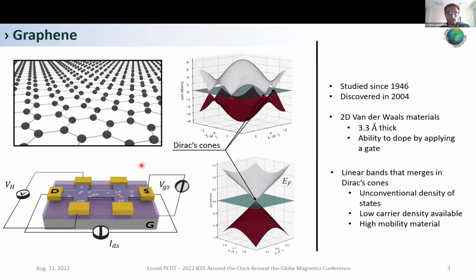But the most striking feature of graphene is its band structure. Here you can see the conduction band and the valence band touch each other at this point called the Dirac cones. Here we have both electrons and holes, and you can remark that the bands are linear. And this linearity involves an unconventional density of states that leads to very low carrier density and very high carrier mobility. And these points are crucial for the Hall effect.